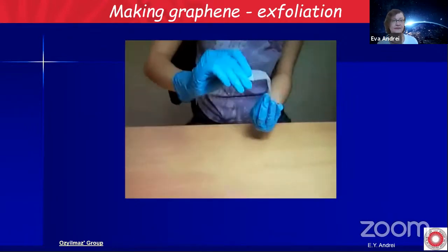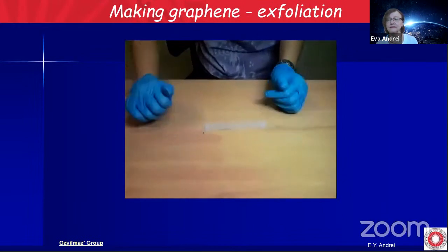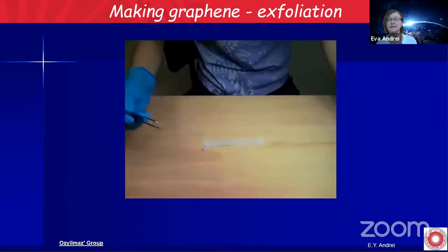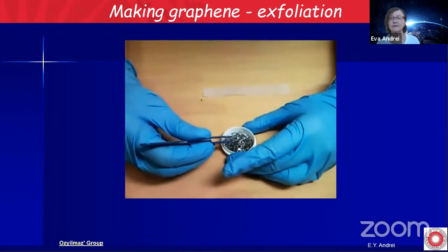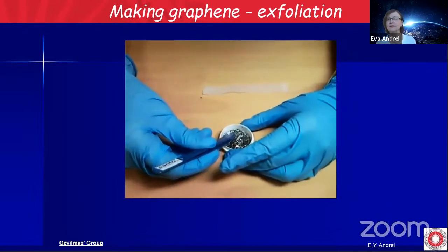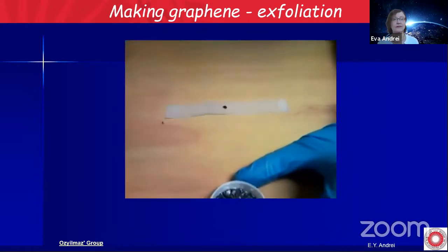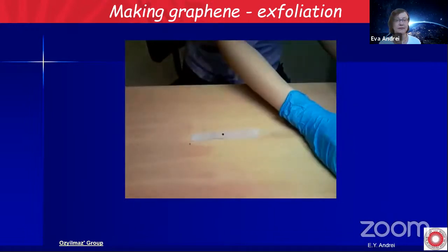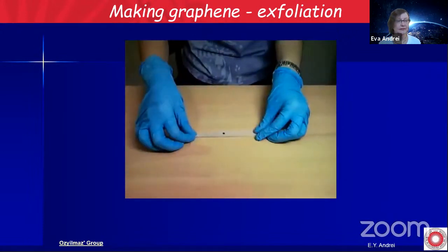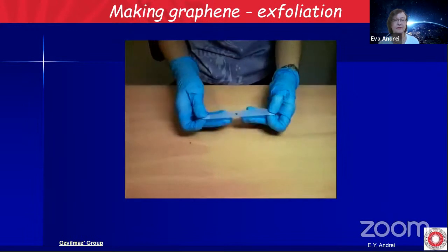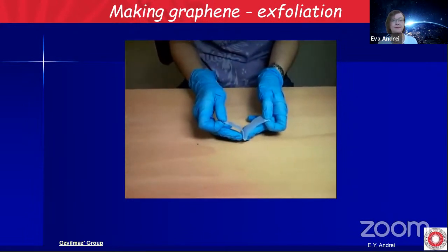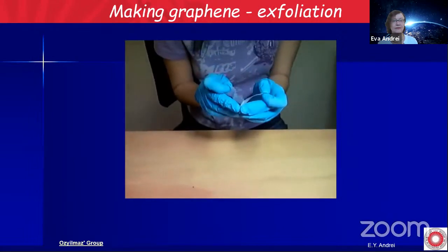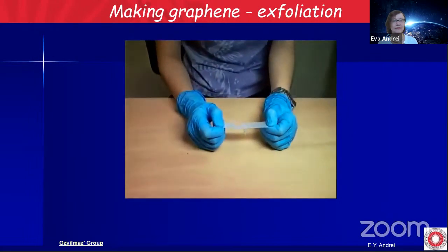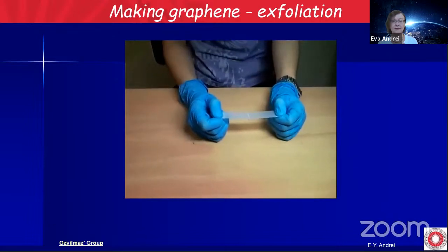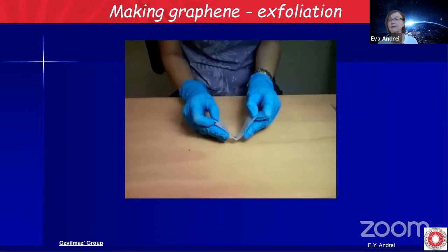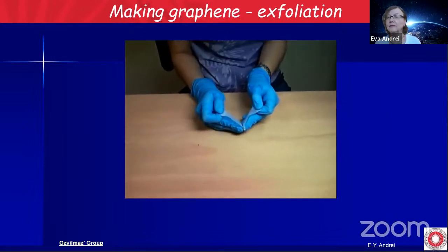Take a Scotch tape and gently lay it down on a flat surface. Next, take clean metal tweezers and pick up a thin graphite plate, and then place this gently onto the Scotch tape. Next, hold the Scotch tape at the edge of the graphite plate. Peel it off gently, and do this step several times until you obtain a nearly transparent region on the Scotch tape.